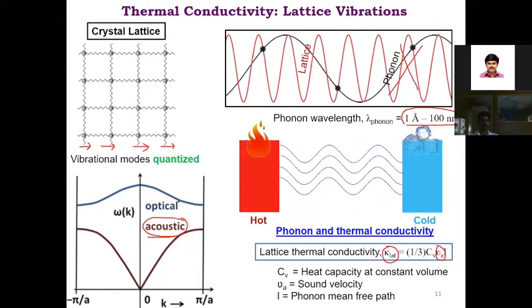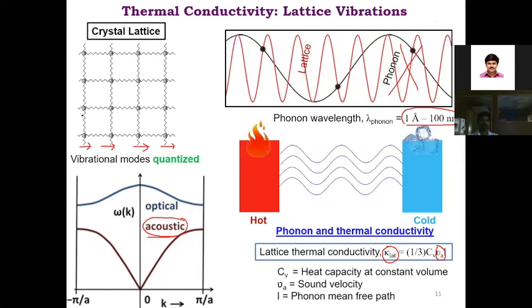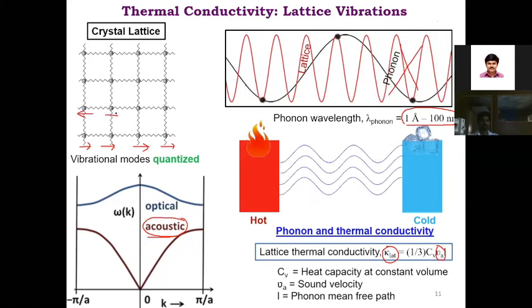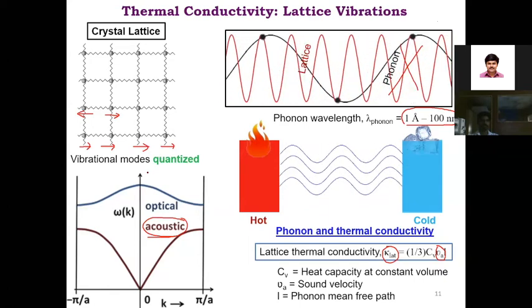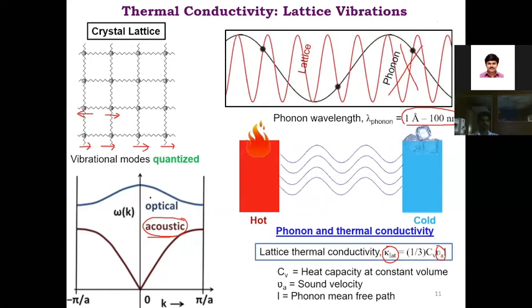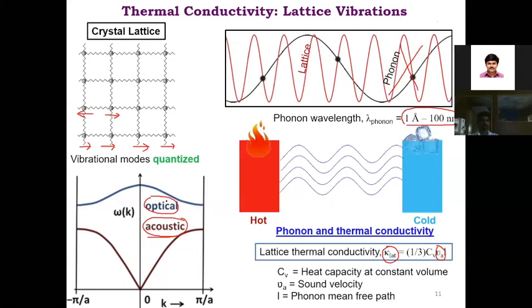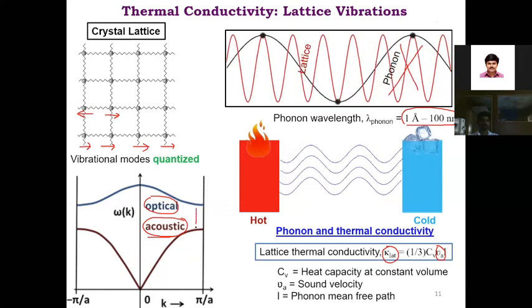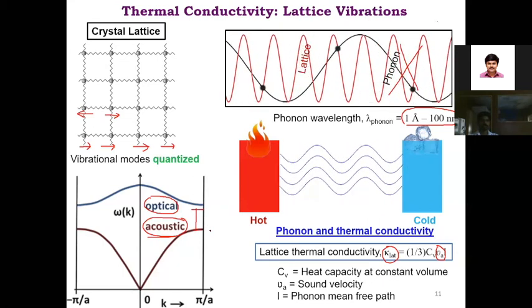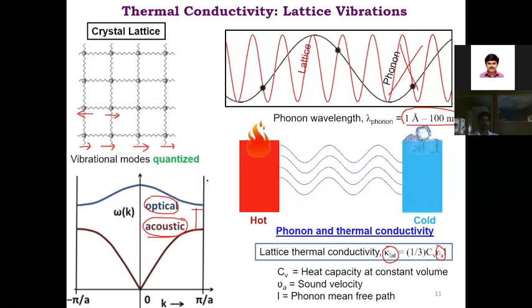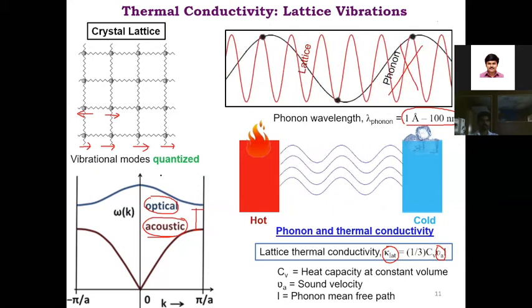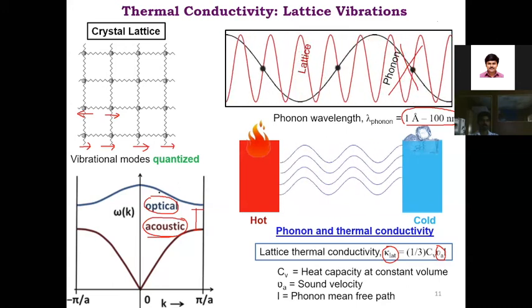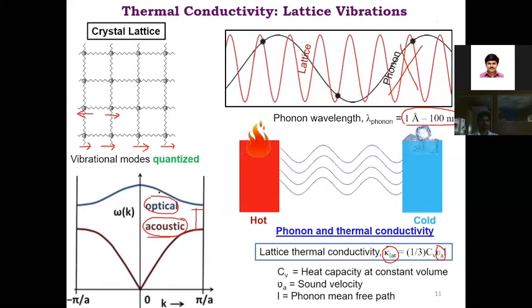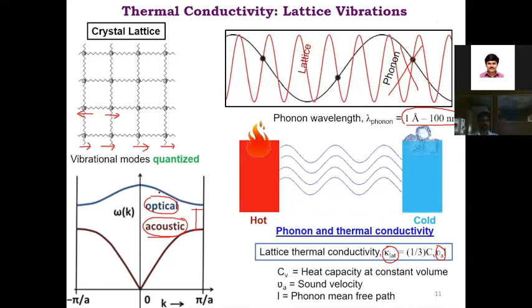There is another kind of phonon which is called optical phonon, and these optical phonons are nothing but atoms in a lattice vibrating in different directions, and this gives rise to a dipole. That's why the name optical came, and it can be determined by Raman spectroscopy, IR spectroscopy or terahertz spectroscopy. But in a normal material, you will always have a gap between optical and acoustic phonon. I'll come back to this slide later in this seminar. But please remember there are two kinds of phonon. One is the acoustic phonon, which is nothing but the sound wave which carries the heat, and the other is the optical phonon, which can be tracked by Raman, IR or different optical spectroscopic techniques.